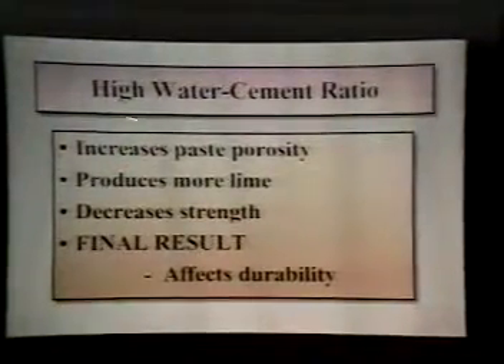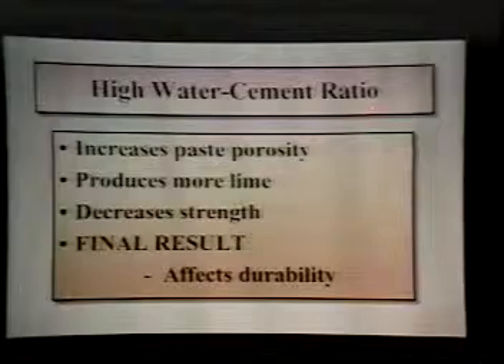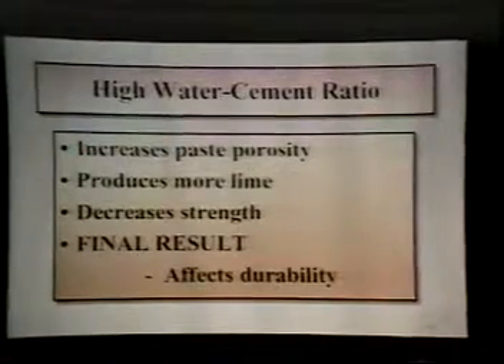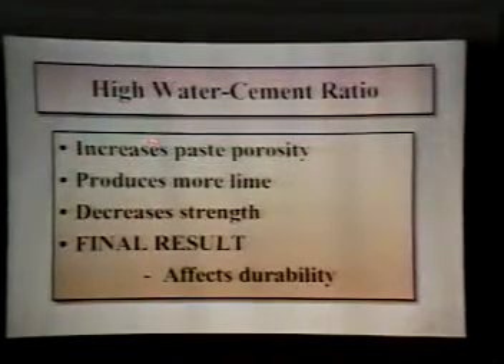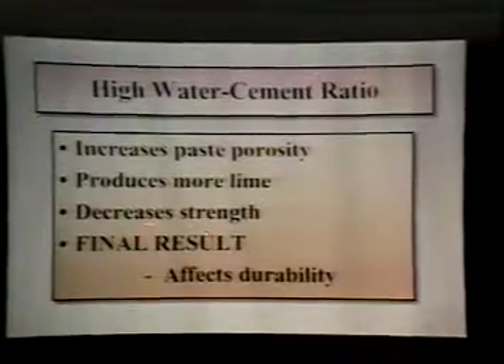Very common problem is high water cement ratio of concrete. It increases the paste porosity. It produces more lime crystals, decreases strength. Final result is it affects the durability. This is the difference between high water cement. This is a high water cement concrete, and this is a dense paste with a low water cement concrete. A blue dye is used to measure the water cement ratio from the blue coloration.